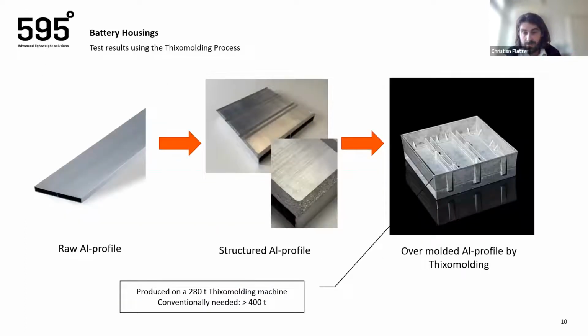But we have been able to produce smaller prototypes with this concept. The box you see here has an edge length of 150 millimeters. We have done a very simple prototype just to prove the basic functionality of the idea and check out how good is the bonding and can it be tight. So we purchased a very simple aluminum profile, a standard alloy, and put the laser structure onto the needed areas, and then overmolded it with the Thixo-moulding process.